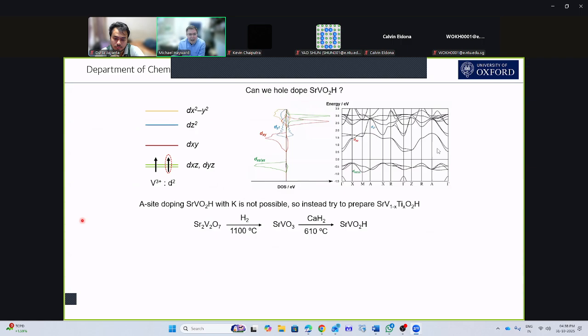So you could think about A-site doping this, so replacing strontium, say, with a lower charged ion like potassium, but that's not possible. Instead, what we're going to do is replace some of the vanadium with a little bit of titanium. And so to make SrVO2H, what we actually do is start by making Sr2V2O7, which is a nice thermodynamically stable material. We then heat this under hydrogen at very high temperature to reduce vanadium 5 to vanadium 4 to make the perovskite, and then we do the calcium hydride reaction.